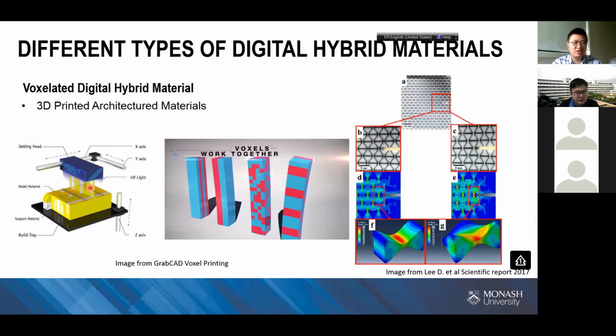So we use PolyJet or other types of additive manufacturing processes. We can control the material distribution voxel by voxel. This is the idea of voxel printing. The blue and red, the different colors, represent different materials. With advanced additive manufacturing, the resolution of each voxel can be achieved to about 20 micron. Each voxel's length, width, and height will be 20 micron. It's pretty small, so we can control the material on a pretty small scale.